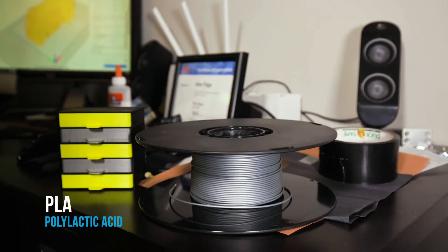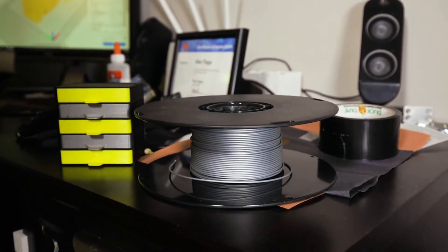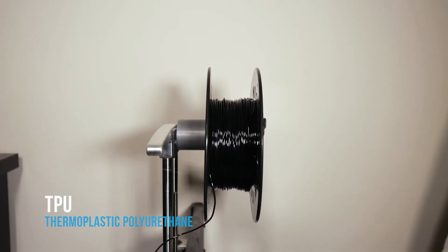We can use different materials. We started with PLA — polylactic acid — which is a stiff, really cheap, really easy-to-use plastic. It almost never clogs and it's the go-to for a beginner with 3D printing. But it wasn't the right material for a drone because it's fairly brittle. When you're flying around at high speeds you need something tougher and more resilient that has some flexibility.